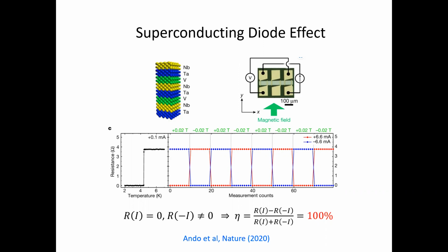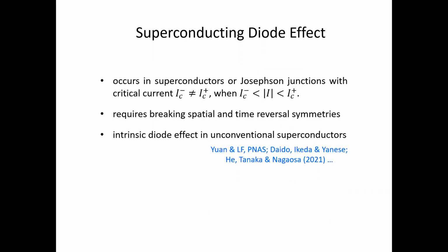Now, interestingly, you notice that at an applied current of 6.6 milliamp, the resistance is zero in one direction, but finite in the other, okay? So this is called the superconducting diode effect. And this creates a very large non-reciprocal effect, right? Resistance is zero in the forward direction, but finite in the backward direction. So if you look at this diode coefficient, it reaches 100%, okay? So this could be interesting.